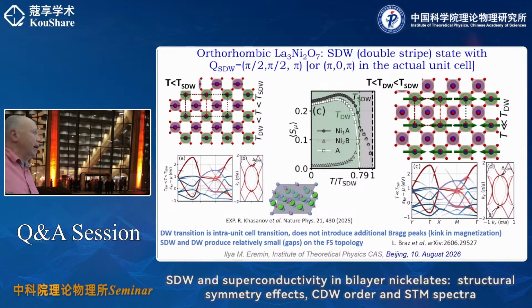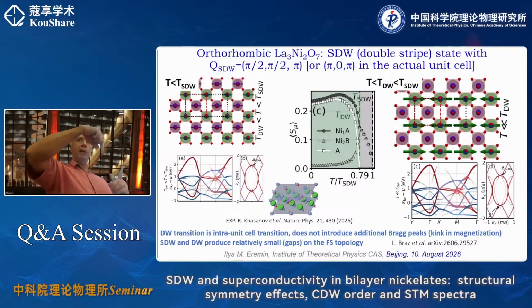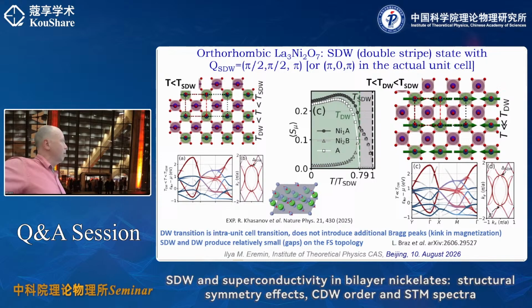Yeah, so what effectively happens is that there is a z square component and there is an x square minus y square component. The magnetization on the x square minus y square and the z square doesn't simply sum up. On one lattice site they add, but on the other one they cancel. So that is what we find. Basically, in one case they add, and in the other case, with the charge order, it yields a compensation. So the amplitudes are comparable. It's not exactly comparable; z square is still larger.